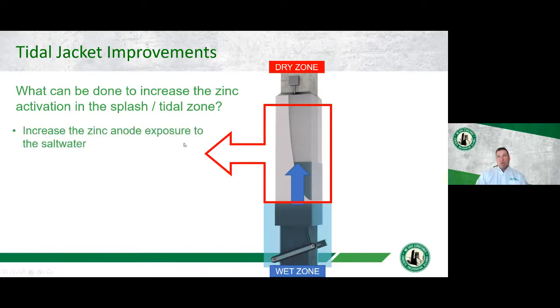Well, there's a few different things that we can do. We can increase the zinc exposure to the seawater. So essentially make sure that it's immersed or encapsulated in seawater, increasing the wet zone. So as the wet zone is increased, or as more and more of the zinc is exposed to seawater, we're going to get an increase in oxidization of the zinc. And so we're going to get an increase in current from our zinc as well.